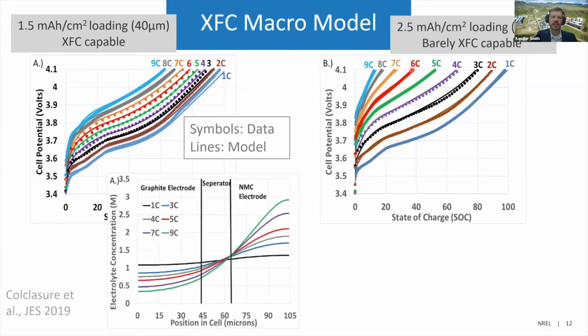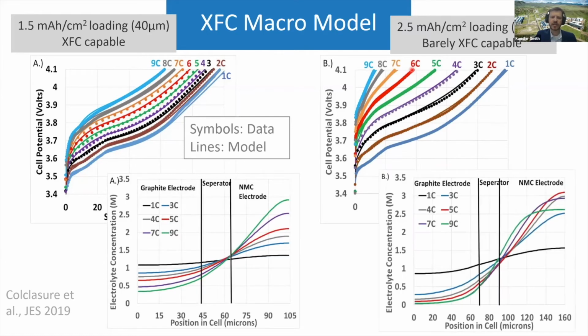The big limitation here is in the electrolyte transport. You can see that under all of these simulations, all the way up to a 9C rate for this thin electrode, you're not reaching the electrolyte depletion condition. Whereas once you're doing 9C rate for the thicker electrode, the 2.5 milliamp hours per centimeter squared, here you're hitting electrolyte depletion in the back part of the electrode. Once that happens, only the front part of the electrode is active. And so whereas you might be charging at a 9C rate on average, the front part of the electrode might see perhaps a 30C rate at the very front.